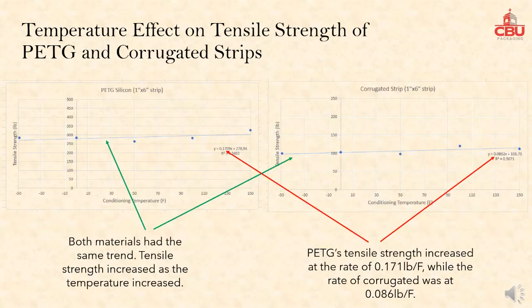As temperature rises, the tensile strength of both PETG and corrugated increases. The PETG tensile strength rises at the rate of 0.17 pounds per degree Fahrenheit, while the tensile strength of corrugated rises only about half the rate of PETG.